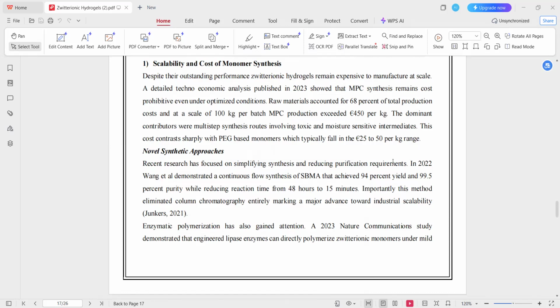A detailed techno-economic analysis published in 2023 showed that the synthesis of MPC, which is one of the most widely studied zwitterionic monomers, remains cost prohibitive even under optimized conditions. At a production scale of 100 kilograms per batch, the cost of MPC exceeds 450 euros per kilogram. Approximately 68% of this cost came from the raw materials, largely due to the multi-step synthesis routes involving toxic intermediates and moisture-sensitive intermediates that require careful handling and purification.